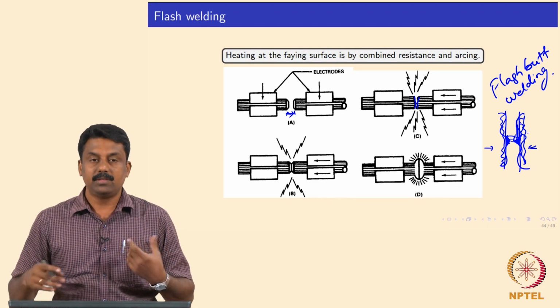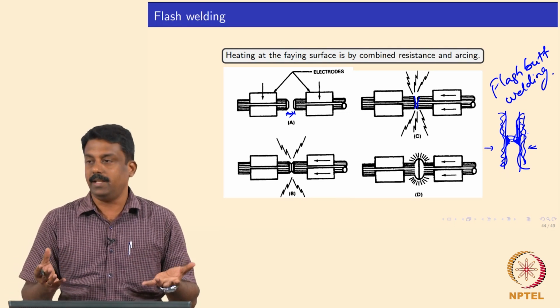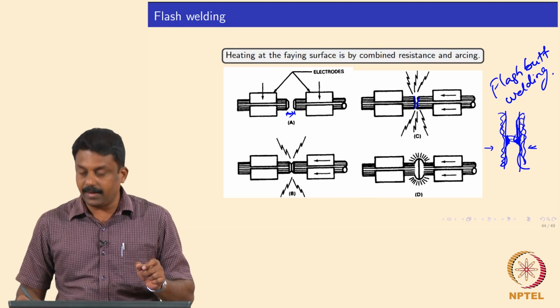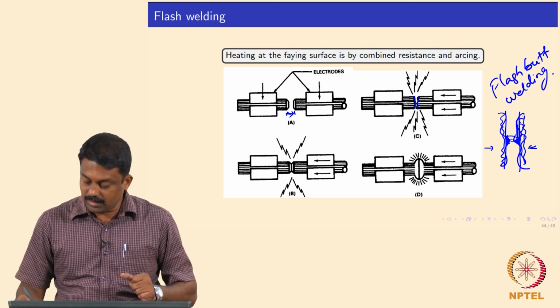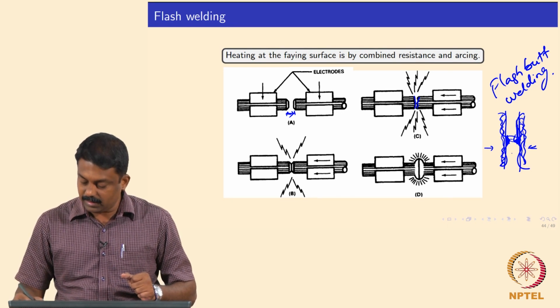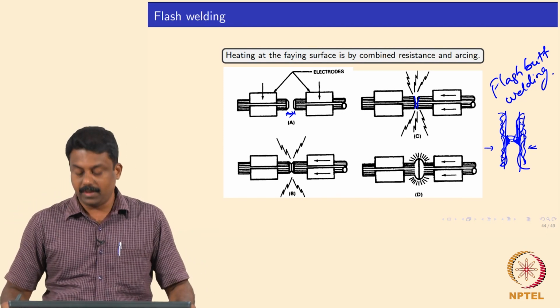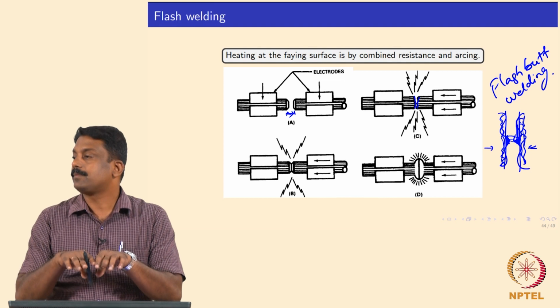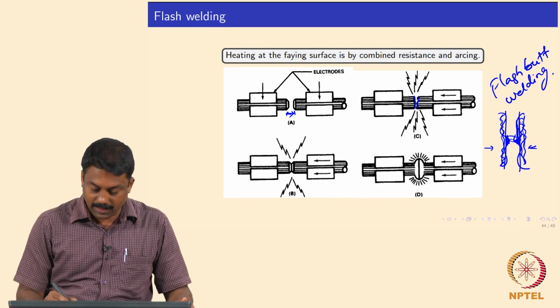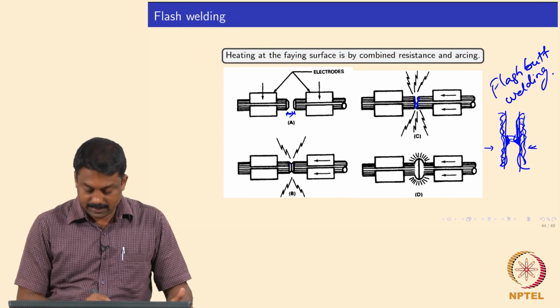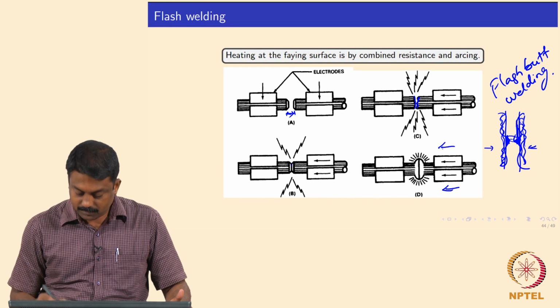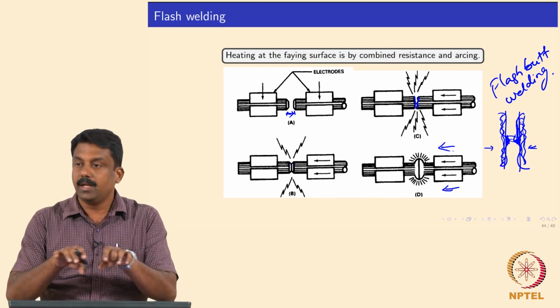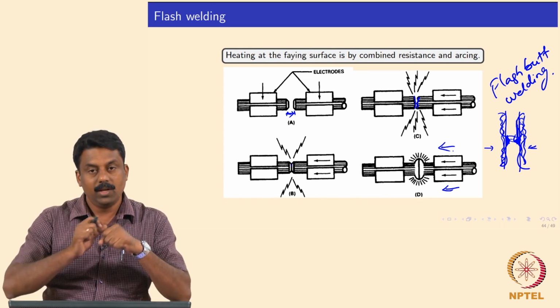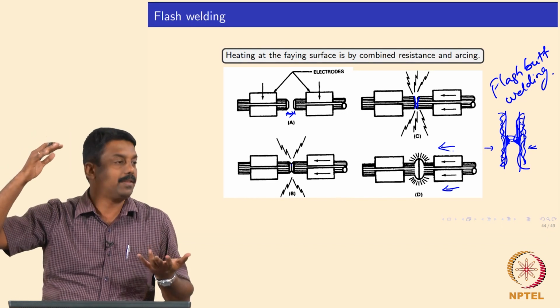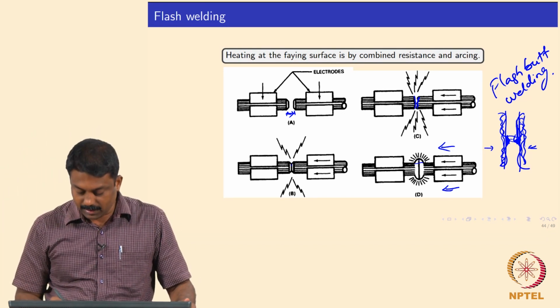That means those regions can plastically flow and mechanically deform much more easily. So you strike an arc, melt the interface, and once you reach a temperature sufficient to achieve the required mechanical deformation, you do an upsetting. You have arcing and melting of the interface, and subsequently you apply a load and have an upsetting. During this process the molten layer at the interface is sent out as a flash. Whatever layer is molten is sent out as a flash, and then the unmolten region coalesces and forms the interface.